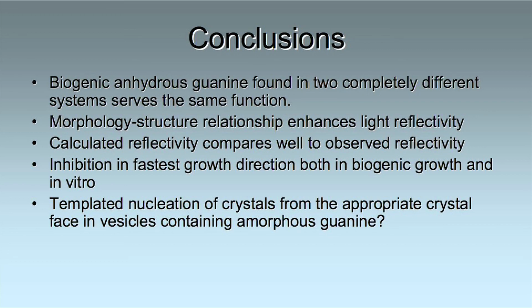I have no idea. The only idea that comes to mind looking at those crystals formed in the vesicle is that we are dealing with template nucleation of crystals from the appropriate crystal faces at the same time in vesicles that contain amorphous guanine. Whichever way it is, and this is something we're looking at right now, we conclude that fish and silver-colored spiders that are very far away in the evolutionary tree evolved efficient mechanisms to control the morphology of the guanine crystal in order to optimize in slightly different manners the reflective properties of the skin, taking into account the environment in which they are, and it's all based on nanotechnology.